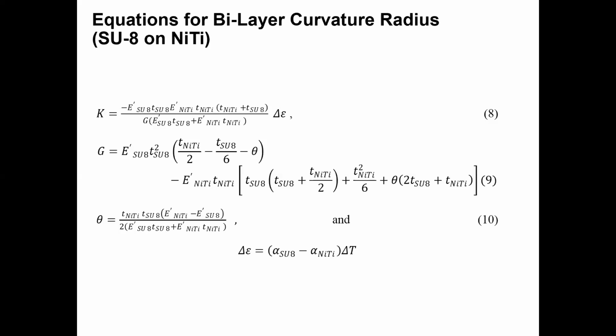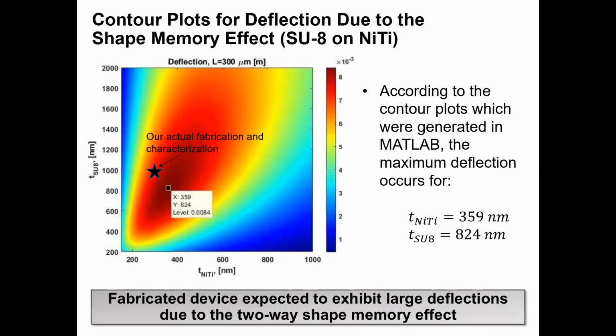So then there's this epsilon term that describes the strain that arises due to CTE mismatch, and the delta T term, which arises from the high temperature processing effects on strain in the bilayer. So from these equations, a MATLAB script was generated and then run through and solved for curvature and deflection due to the shape memory effect. So the contour plot here in this case describes the deflections expected for a NiTi and SU8 cantilever bilayer of fixed length.